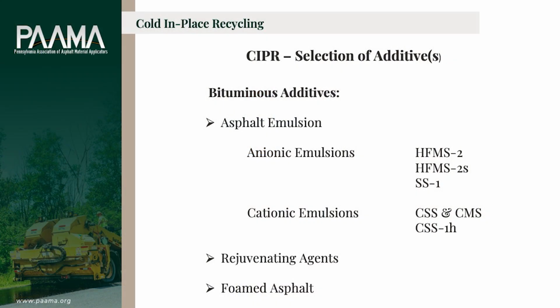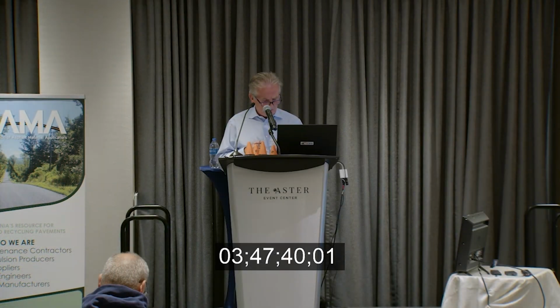Selection of additives. Well, the asphalt emulsions that we use are cationic. We've talked about that this morning in several of the presentations. We use a CSS-1H, which is a cationic slow set emulsion. Rejuvenating agents, we don't really get involved with. Foamed asphalt, that's a whole different sphere. It hasn't been really used a lot in Pennsylvania, but I know in New Jersey they have experimented on a few projects. But you need a whole different system. It's where you're taking a hot AC and you're adding very cold water, you're making an expanded asphalt, and that is what is dispersed into your materials.